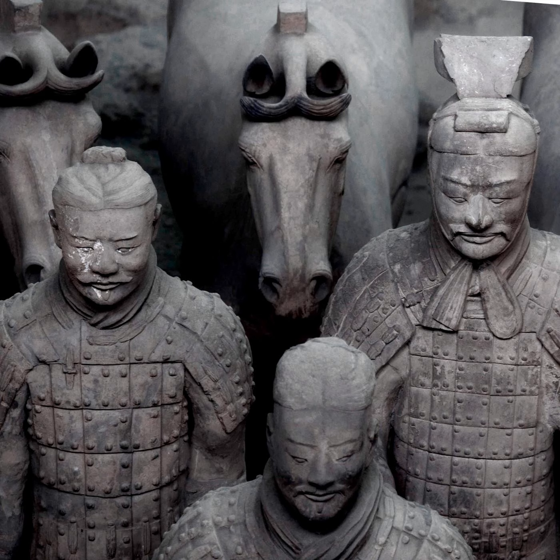Sintering is when you have two clay particles that touch each other, right? And of course, these clay particles at 800 degrees are very, very hot. And the points of contact between these particles are so hot that they sort of fuse together with each other. And once that happens, your clay is no longer clay, but a material that we call bisque, or sometimes biscuit, right? And here's the thing.